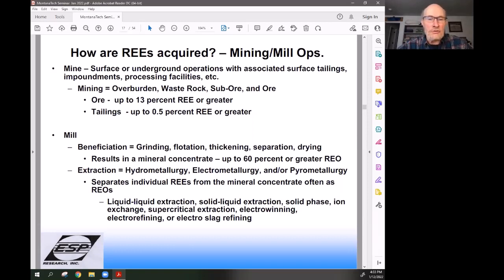In the mining world, you have to get the overburden and waste rock away from the place, and then you have ore that can be fairly rich, anywhere from 13% by weight or more of rare earths. And then the tailings, in some cases, are 0.5% and maybe up to 3%. What's interesting at Mountain Pass is that their old tailings are 8 to 10% in rare earths. That's what they threw away. And the balance of the rare earths they pulled out, they tend to be around 18 to 20% in their concentrations. At the mill level, that's where the process of beneficiation takes place.